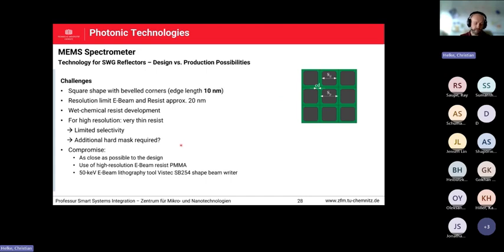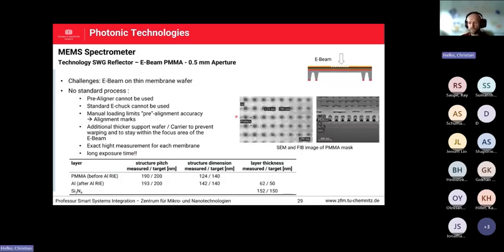But together with the simulation guys, we decided, because it's an e-beam process with a wet chemical resist development, there will definitely be a rounding. We want to go with thin resist, but then you have this limited selectivity due to etching. A lot of discussions were carried out, and we decided to go with the design as close as possible, meaning that we want to expose rectangular structures, and we use our e-beam with a PMMA resist layer. And that is what we ended up with after the e-beam litho itself.